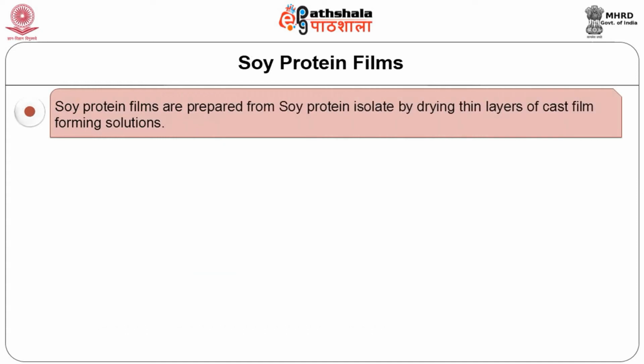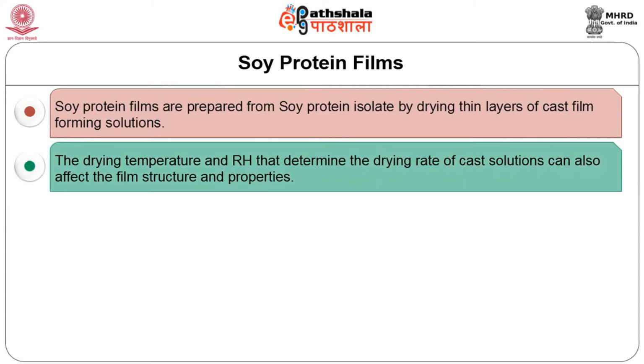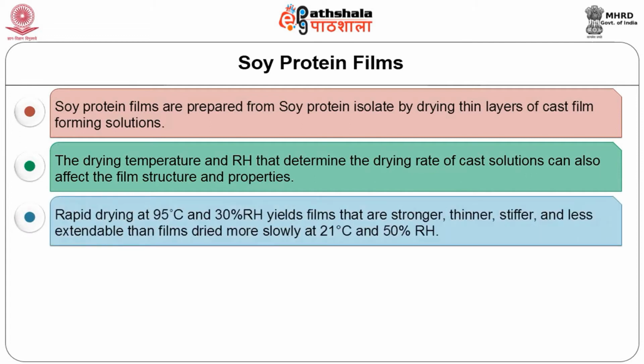Soy protein films are prepared from soy protein isolate by drying thin layers of cast film forming solutions. The drying temperature and relative humidity that determine the drying rate of cast solution can also affect the film structure and properties. Rapid drying at 95 degrees Celsius and 30% relative humidity yields films that are stronger, thinner, stiffer and less extendable than films dried more slowly at 21 degrees Celsius and at 50% relative humidity.